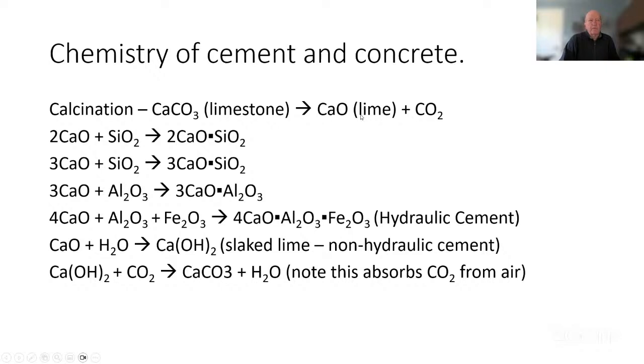This is a process that, first of all, you can see it right there. It drives off a whole bunch of carbon dioxide, and in doing that, we're creating a climate issue. In addition, you have to raise this to somewhere in the neighborhood of 1,500 degrees Celsius to accomplish this reaction, so it takes a lot of energy to get up to that temperature. Roughly speaking, about half of the CO2 emitted in this process comes directly from the limestone, and about half comes from the energy that you have to supply, usually in the form of coal or something like that.